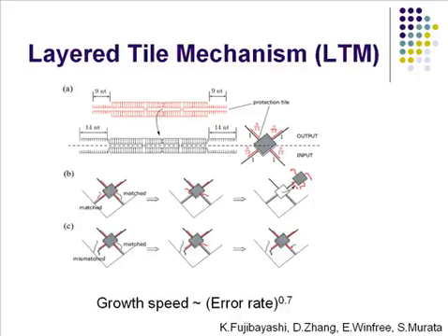So it remains in place, and this doesn't allow additional association of other tiles. And the bonding strength itself is quite weak, so this complex will be dissociated. By this mechanism, we can reduce the error rate further.